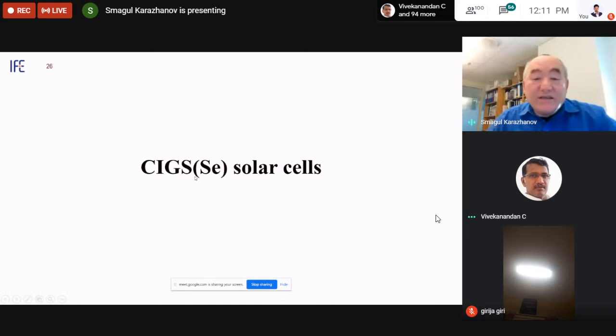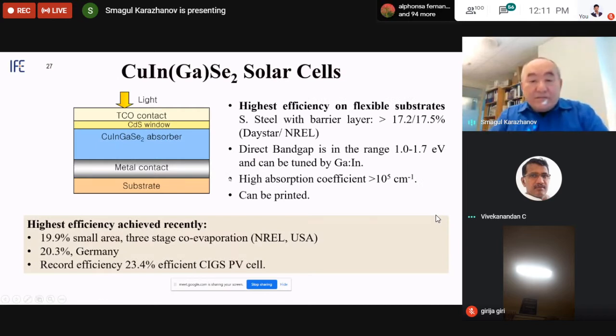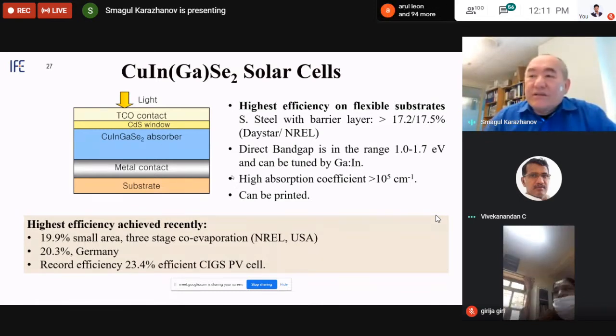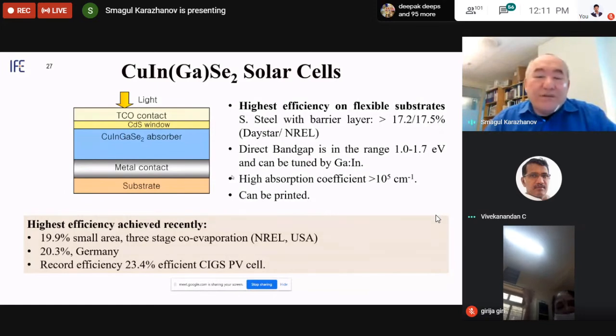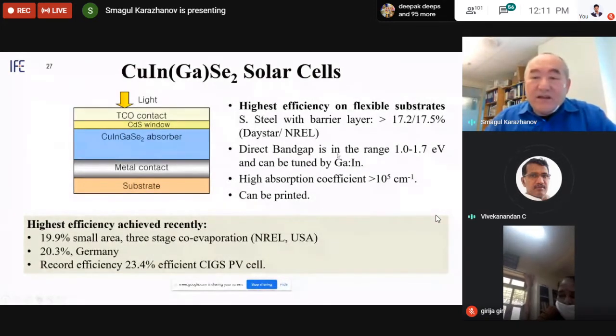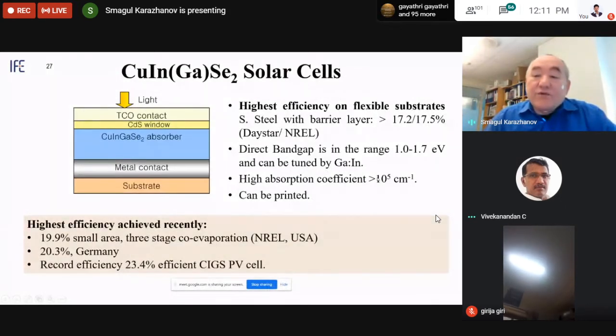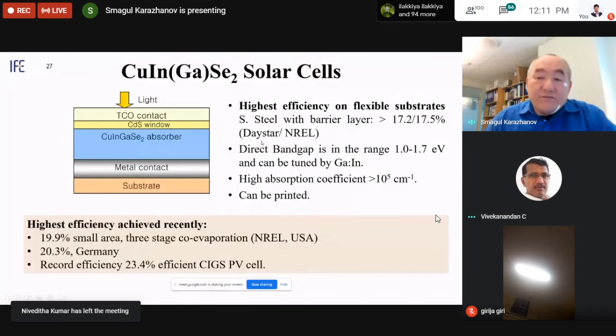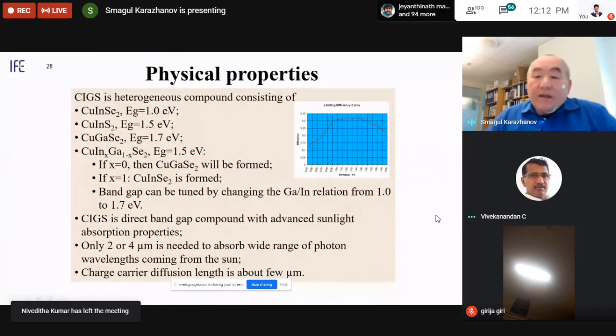The next candidate is CIGS: copper, indium, gallium, sulfide or selenide. Yes, this is a direct bandgap semiconductor. It can absorb sunlight with just about 2 micrometer thickness. CIGS can absorb almost the same light as 250 micrometer thick silicon. So it is really a lightweight solar cell. And its absorption coefficient is very high compared to silicon. It's high, and now efficiency is quite high also. And the band gap can be tuned by controlling the ratio of gallium to indium, and then the band gap can be tuned from 1 eV up to 1.7 eV.